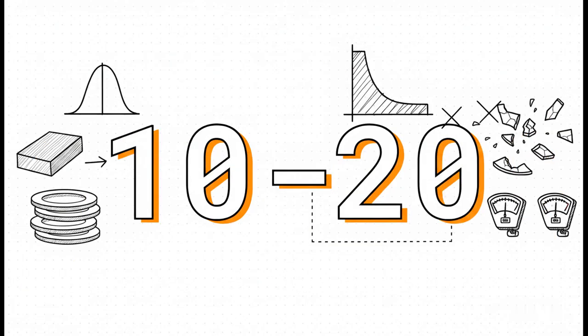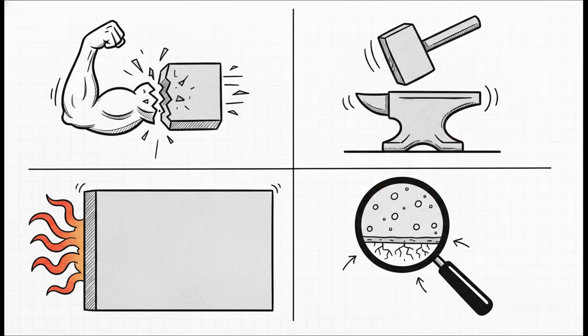Now, this number, 10 to 20, is the Weibull modulus of high-grade zirconia. In engineering circles, the Weibull modulus is a statistical measure of reliability. Usually, ceramics are notoriously unpredictable, right? You could test 10 identical ceramic plates, and they might all break at totally different force levels just because of random microscopic flaws. But a Weibull modulus of 10 to 20? That proves zirconia is exceptionally consistent and predictable, and that is a very rare, very prized trait for any ceramic material. So to quickly summarize its extremes, high-grade TZP can hit a flexural strength of up to 1.2 gigapascals and a fracture toughness of 7 to 13 megapascal root meters. That absolutely dwarfs standard ceramics like alumina. It's strong, it's hard, it's highly insulating.